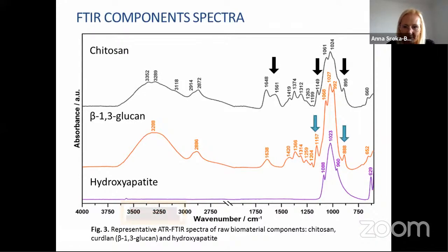So we see the differences in the spectra and the bands, which are in different positions. Here are the indicating points which we use as a fingerprint. We can even notice the shift in the main peak bands of the hydroxyapatite. Then we analyzed the ATR-FTIR sample spectra, which were native, control, ADSC, and BMDSC. You can see the different lines, and we can compare the lines with ADSC and BMDSC, which are with the stem cells, and the native and control, which are the experiments where cells were not used. So adding the cells makes a difference in the shifting bands, even in the lipids and in the amides, of course, which is quite obvious.